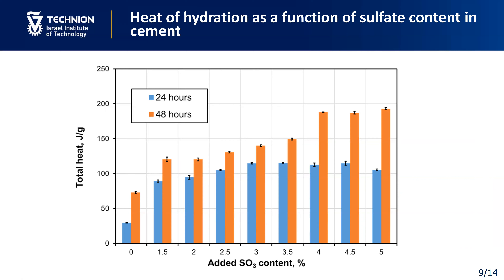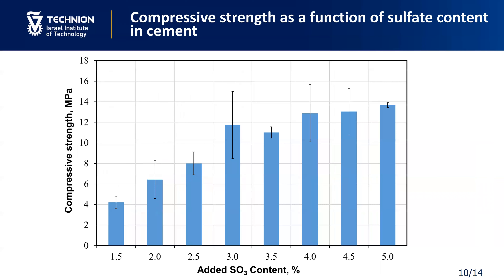The difference in data between 24 and 48 hours can be explained by aluminate depression after one day. The compressive strength demonstrates a trend of increase with the increase of sulfate content. The increase in strength is steep between 1.5% and 3%, but between 3.0% and 5%, the increase becomes only moderate.